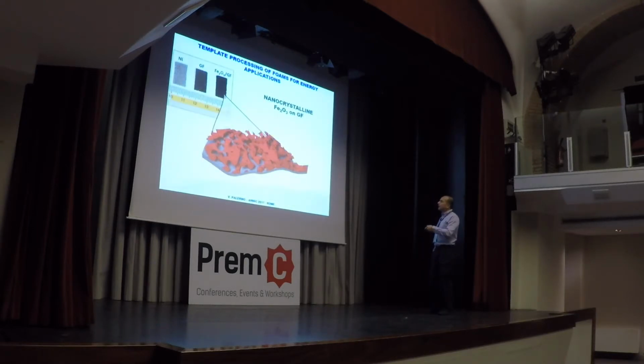Then you can remove the metal. What you obtain is a highly conductive, highly porous electrode, functionalized with this porous layer that is ideal to store lithium, while this is ideal to collect charges and bring them out of the battery. And this is how they look, so you can do it in pretty large pieces. Here's the original nickel foam. This is the graphene foam, so without any metal, and this is the graphene foam together with the iron oxide.